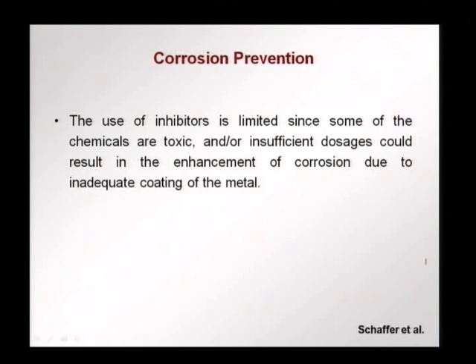Some limitations in the use of inhibitors are that the chemicals are toxic, some of them at least, and therefore we cannot have them be in contact with people. Secondly, if you have an insufficient dosage, if the dosage is not enough for the exact type of corrosion that is occurring, the corrosion can be enhanced, and also we will believe that the corrosion is going to be inhibited and it will not. So, these are tricky aspects related to the use of inhibitors, and therefore, there are limitations on where these inhibitors can be used.